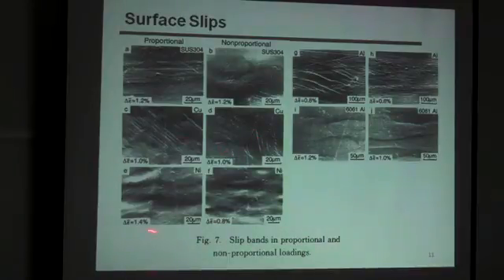And in this nickel, no slip lines found at all. And in aluminum, 6061 aluminum, no slip, but maybe squaring up or sinking down of the grain boundaries, looks like here. One exception is the pure aluminum. We found a slip line on the surface. So I can't understand why. But you can understand multiple slip lines operated for stainless steel. So that is the main cause of the high additional hardening.